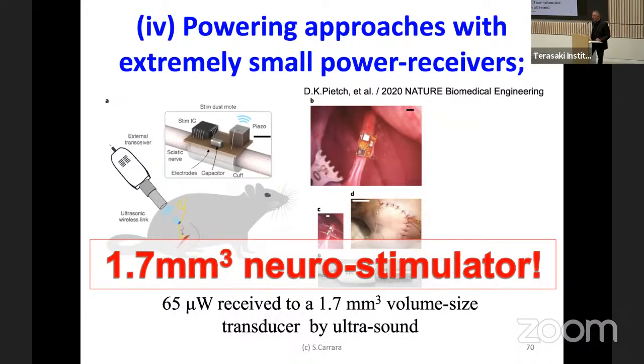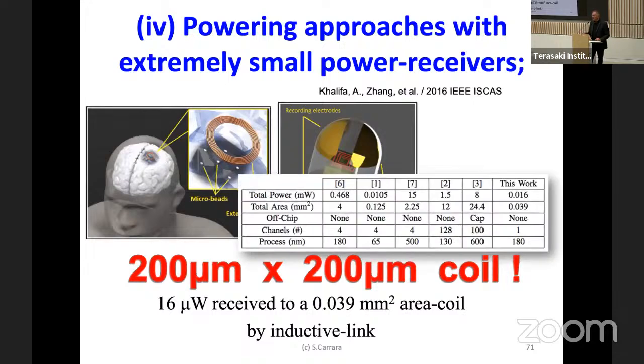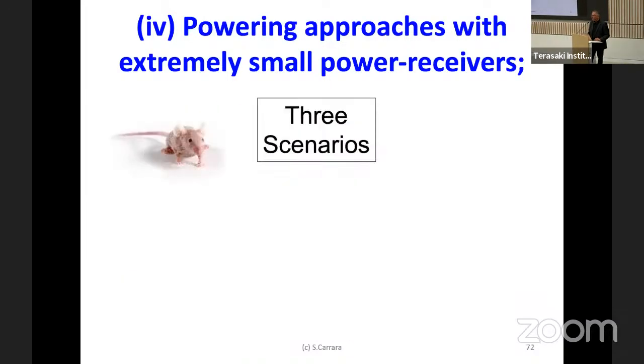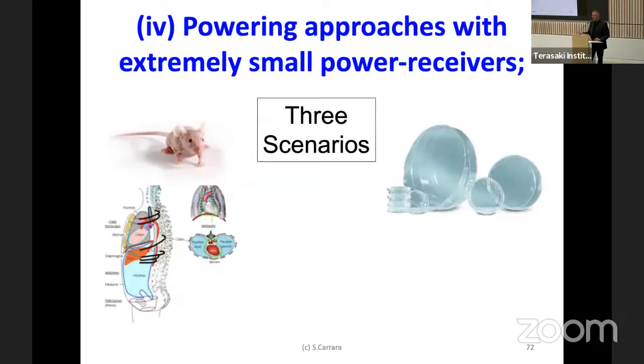This is the stimulation of the sciatic nerve, but they did it with a 1.7 millimeter cube powered by ultrasound. It's several orders of magnitude too big with respect to our needs. So we went back to the literature, and we discovered that another good friend of ours, Ralph Etienne-Cummings, already did years ago a 200 by 200 micron coil that received enough power for stimulating brain electronics. So we started from that work, and we imagined three scenarios for our body dust.